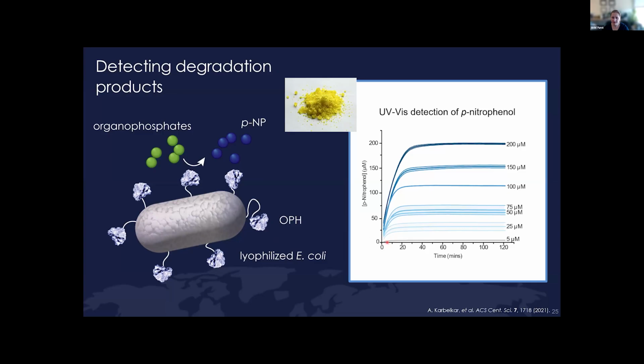And that was really the only way we could actually get kinetics out of this data, because this reaction occurs so quickly because we've stabilized those proteins on the surface. So what I'm showing on the right here is just UV-vis detection of this small molecule. This is that p-nitrophenol, that yellow molecule that's generated after you cleave the organophosphate pesticide. And so this is the concentration of our pesticide. You can see in all cases, we basically get 100% degradation, so full generation of that p-nitrophenol.